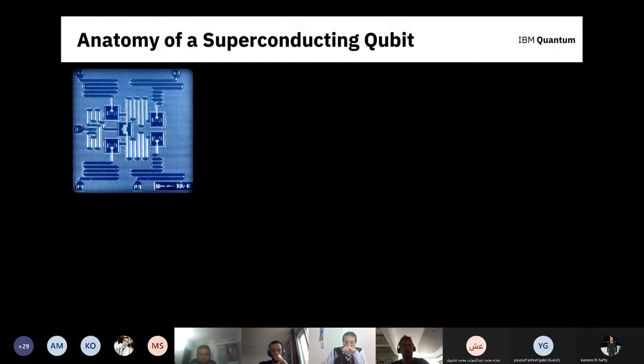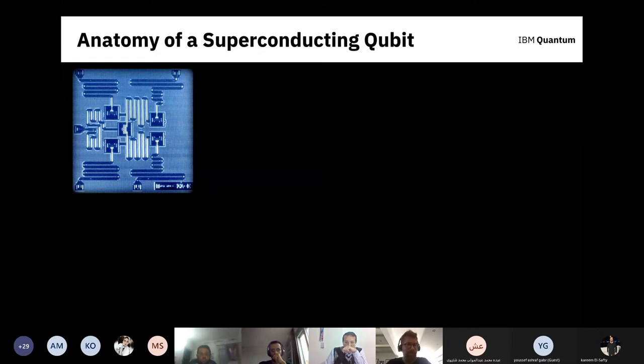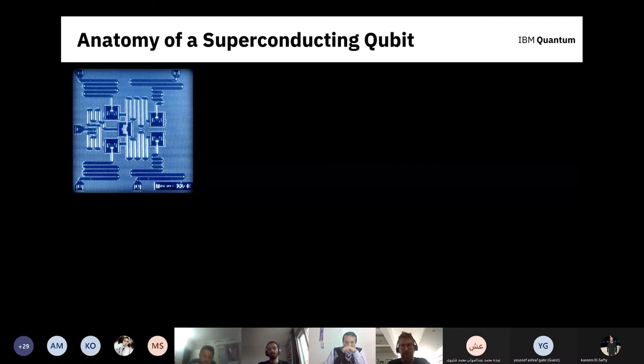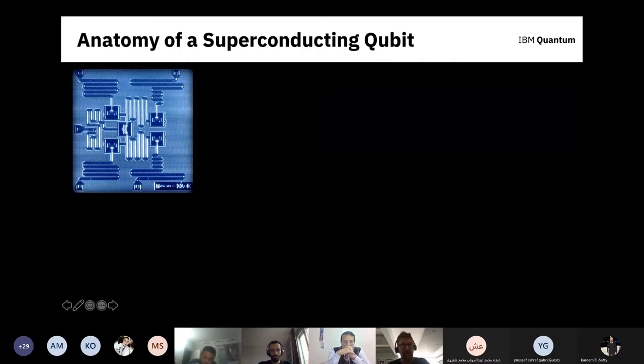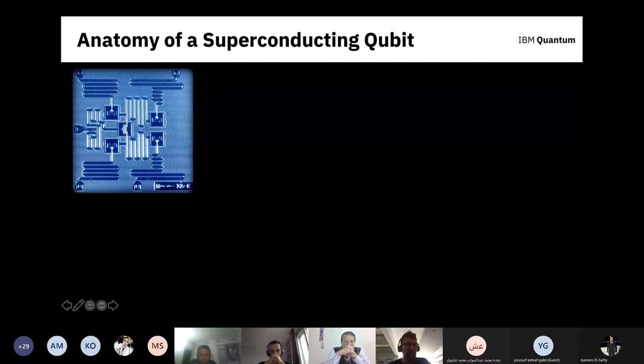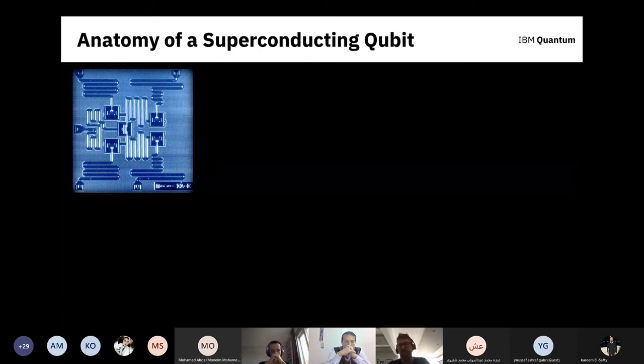Now I'll go into the hardware. We leverage many techniques developed from classical computing, such as microfabrication and nanofabrication, working with silicon wafers to build superconducting circuits as opposed to semiconducting circuits. A superconductor is a metal that loses all electrical resistance below a certain temperature. What you see on this chip are two superconductors — we use niobium, which becomes superconducting below 9 Kelvin. We've patterned most of the large features on these chips out of niobium because it's a very good superconductor. This is a five-qubit superconducting device, very similar to the one we put online almost five years ago.